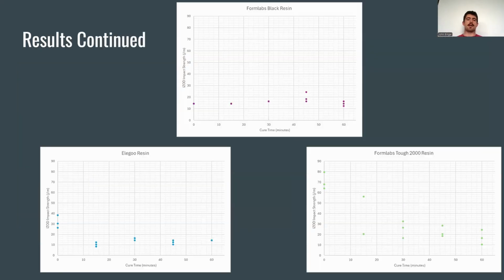The ending angle of the swing arm, change in center of mass height, change in energy, and two versions of the IZOD impact energy number are listed. Each resin had its own trend with curing time, as shown in the data from the experiment. Each curing time had 3 specimens that were tested, and the average impact energy was used to represent that curing time. The average IZOD energy values for Elegoo with no cure were 31.75 joules per meter and 14.4 joules per meter for 60 minutes of cure.